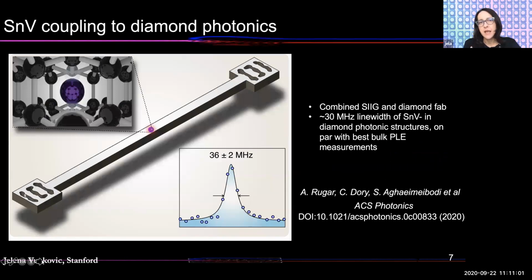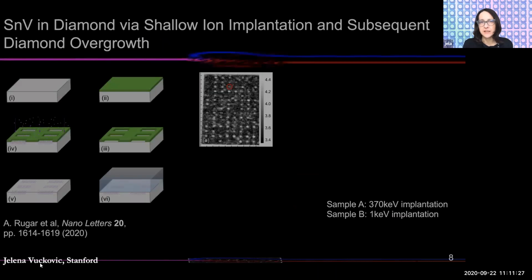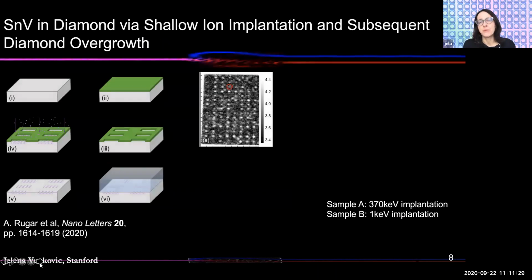So we're able to put them inside of the optical structures, optical waveguides in this case, which are outcoupled with grating couplers without degradation of line width. The line width of the tin vacancy color center is about 36 megahertz after embedding inside of the structure. So we are working further on scaling of these systems, but we're working with optically interfaced spin qubits.